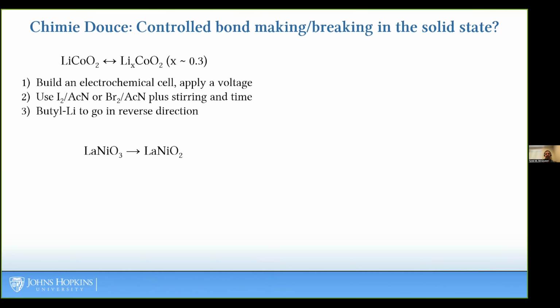With respect to superconductors and the nickelates, right? So here's a transformation that you want to do in that field, which is to go from the perovskite LaNiO3 to this layered, so-called infinite layer, but it's just a layered oxygen-deficient perovskite, from LaNiO3 to LaNiO2. And there was work that was done about 25 years ago that pioneered a very clever way to do this, which is to basically use a hydrogen-containing reducing agent, calcium hydride or sodium hydride, and very carefully controlling the temperature, going to 280 Celsius. And if you went 5C hotter than that, you decomposed the material, and if you went 5C lower than that, you didn't get a complete reaction.